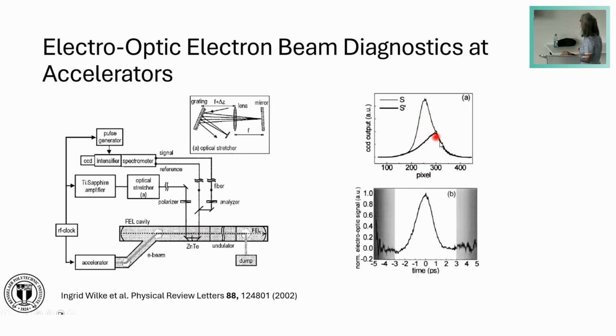And this is the example. This peak is the measurement with the electron beam present, and this is the signal. This is the reference measurement. If we subtract those two spectra from each other, we get the electron bunch length. At that time, the pulses at FELIX were about 6 picoseconds full length, and the full width at half maximum was somewhere, I don't know, maybe 2 to 3. And I think the bunch charge was on the order of 100 picocoulomb.